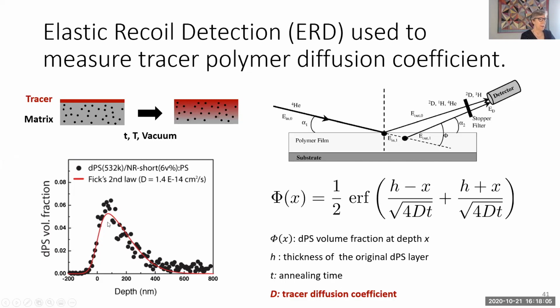And so this concentration profile can be fit with Fick's second law, and the only unknown in this equation is the diffusion coefficient. We know the initial thickness, we know how long we annealed it, we've measured the concentration profile as a function of X, and now we just have the diffusion coefficient.